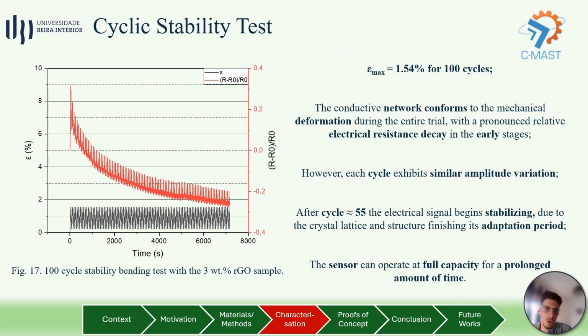Therefore, to deepen our knowledge on the conductive network's conformation, the stability and prolonged use, as well as the influence of the viscoelasticity, a sample with 3 wt.% rGO was subjected to a 100-cycle stability test. A pronounced conformation period was observed until halfway through the test, where the relative electrical resistance dropped, possibly due to the low strain used. However, from cycle 55 onwards, the signal began to stabilize, which showed us that the material was able to adapt well to the induced mechanical strain.